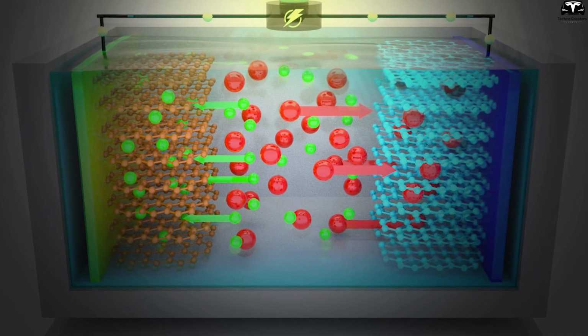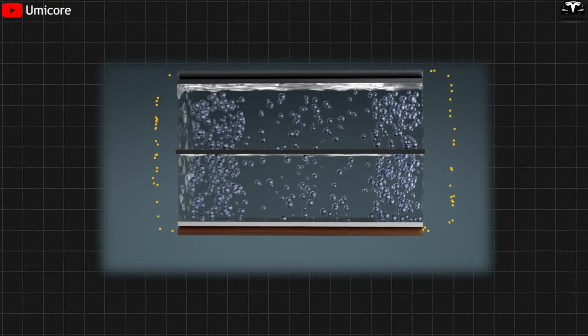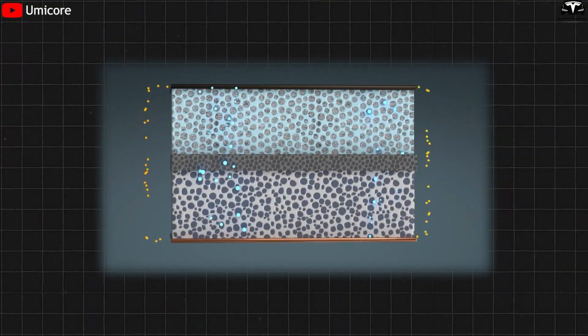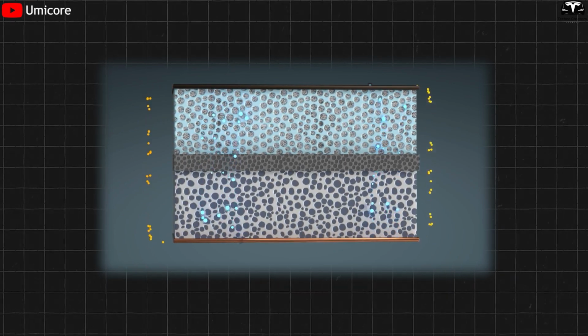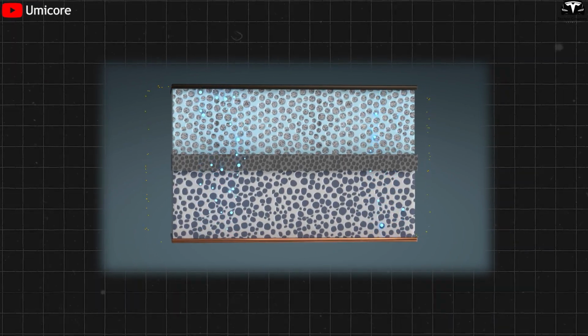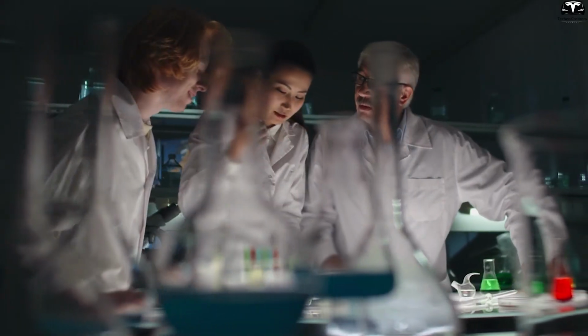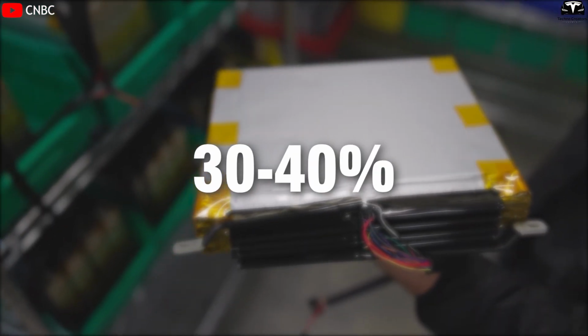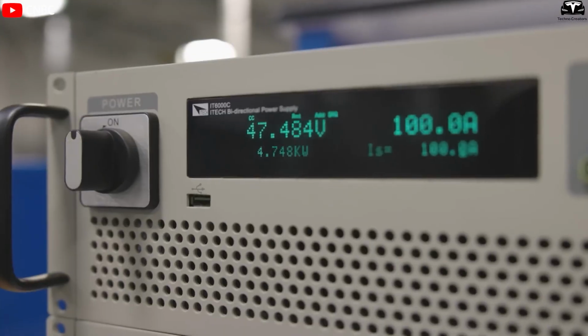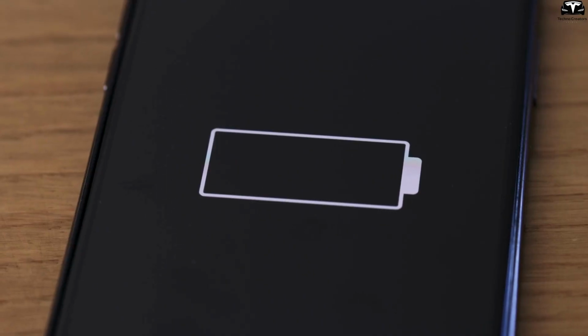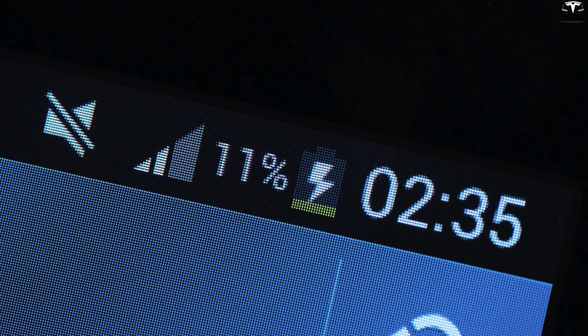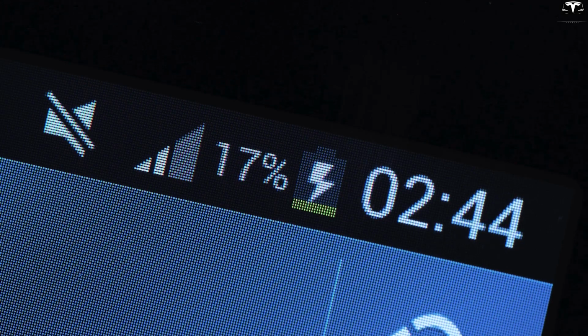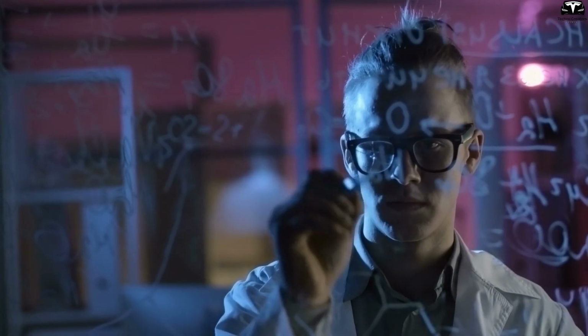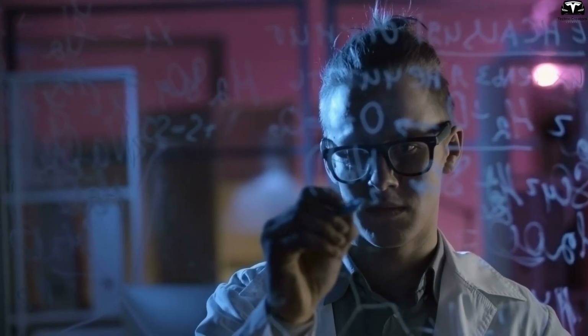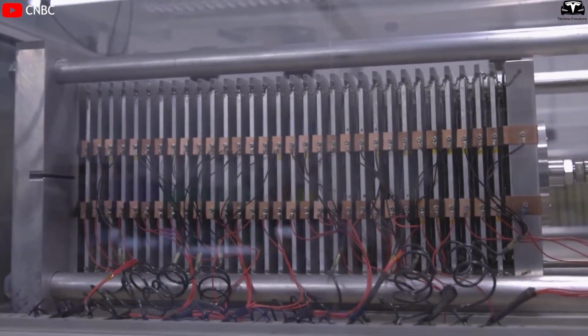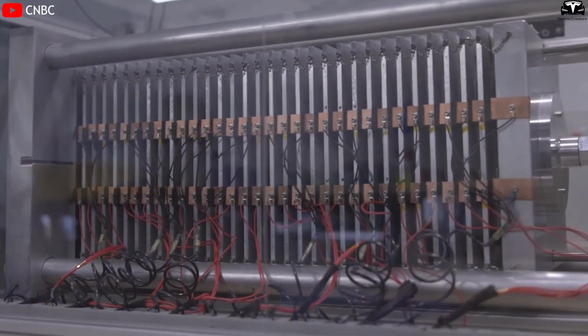In organic batteries using traditional aqueous electrolytes, free water tends to diffuse and react with electrode materials, leading to charge loss and damage to molecular structures. Recent studies have shown that organic batteries with aqueous electrolytes lose up to 30 to 40% of their voltage after just a few hours when left at open circuit. This makes devices using such batteries unstable, unable to store charge for long periods, and very difficult to commercialize. This is also why most previous studies, despite achieving good capacity, either do not publish or deliberately ignore the self-discharge rate, a serious but rarely mentioned problem.